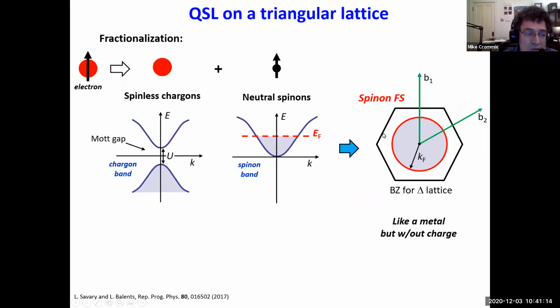If you have a quantum spin liquid on the triangular lattice, then we expect electrons to fractionalize into spinless chargons and neutral spinons. The chargons are gapped, because in order to create a chargon you have to supply enough energy to overcome the Mott insulator energy gap. So they're gapped out, but the spinons are not. The spinons are free to move around, like free electrons. They're neutral, with no charge, but they're free to move around. And because they're fermions, they fill up a band up to a Fermi level. So they have a Fermi level.